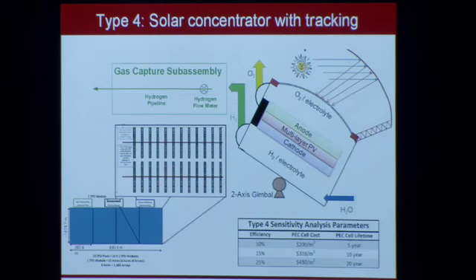And then finally is that same type of device design, but now we're going to use concentration. We're going to put some parabolic mirrors that are going to accept that sunlight and send it down into our photoelectrochemical material. We don't need as much material now because we're concentrating that light and we're heating it up as well, which makes it easier to split water, so we can go with higher estimates on what the efficiency of such a device is, but it's going to be a little bit more costly because this device is actually pressurized in situ. And this device is sitting on a 2-axis gimbal so that you can be constantly tracking the sunlight.